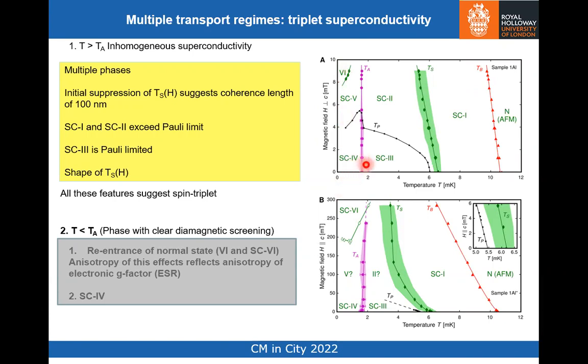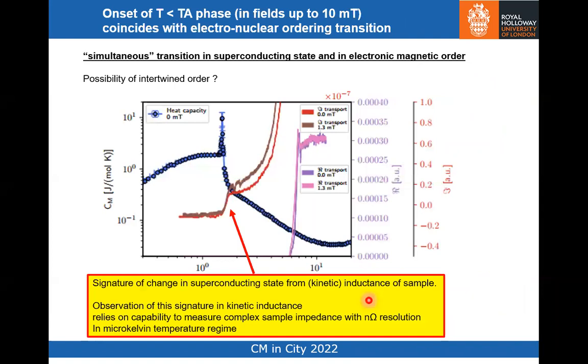And what is robust between these two field orientations is this phase that I'm going to call, this is local labeling, SC4. So the phase that you see as you cool below TA in zero magnetic field is seen in both field orientations and is relatively robust.